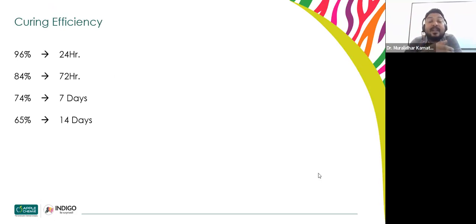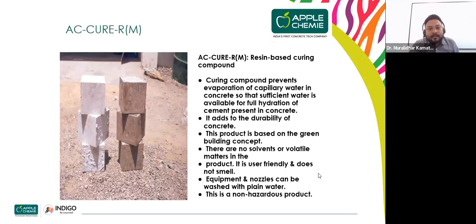The curing efficiency, see, on the first day when you check the evaporation losses, the curing efficiency will be high, like 96%. Then after 72 hours when you check, it is going to diminish from the surface. Whenever we apply curing compound, it will get removed a little bit. Then after 7 days and for 14 days, your curing efficiency will be 65%, because the membrane curing paint we apply over there will get removed. And here you can see the white, with curing compound and without curing compound. You can check over here.